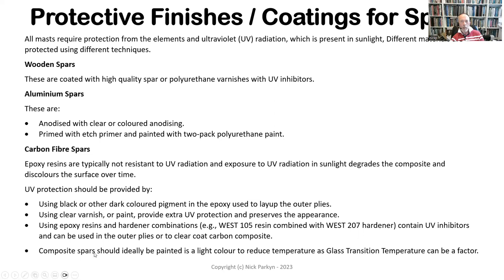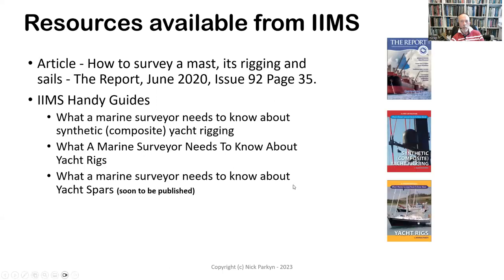But equally, you've got to be careful, depending on the manufacturing technique of your spar, because natively carbon fiber spars are black, and so they will experience a lot of heating from the sun. And there is something called the glass transition temperature, where, depending on the resin type you're using, you can get very close to the temperature where the resin starts to not be rigid anymore. It starts to become more flexible, and this has been a factor in composite aircraft that are typically only painted a white color. Obviously, this problem is more prevalent in horizontal surfaces, and typically masts are vertical surfaces. But again, it's something that we could look at.